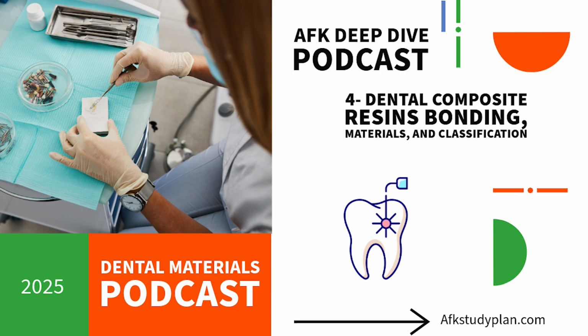Okay. But dentin is different. It's got more organic stuff, collagen, and it has tiny fluid-filled tunnels. Right. The video mentioned if you dry dentin too much, the collagen network exposed by the acid just collapses. Exactly. Flattens down like a deflated sponge, and it forms this sort of impermeable layer. The resin just can't get in properly. And that means a weak bond or no bond.